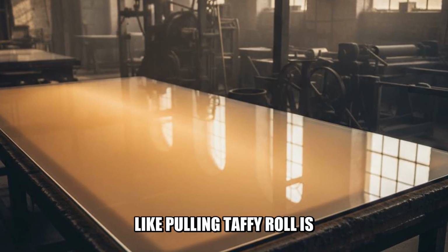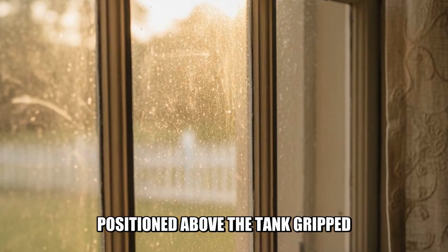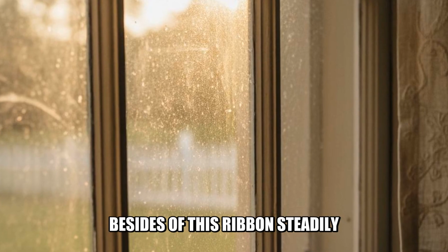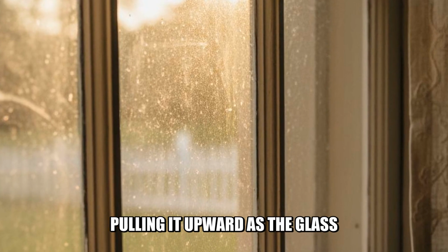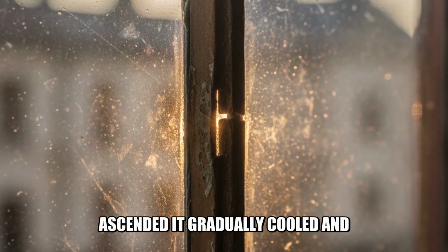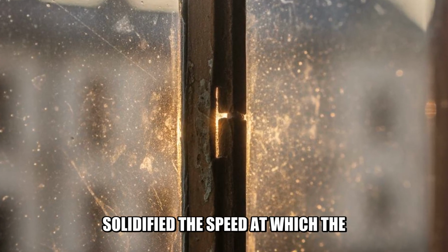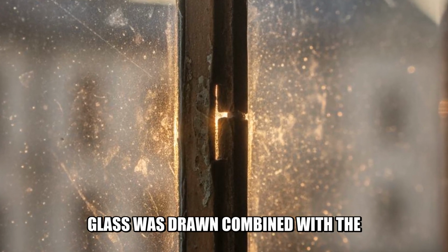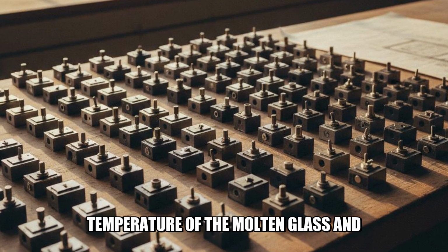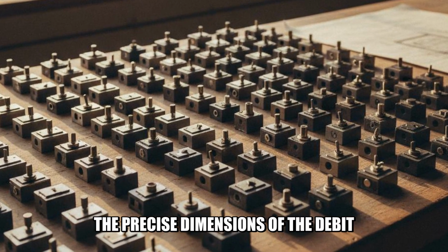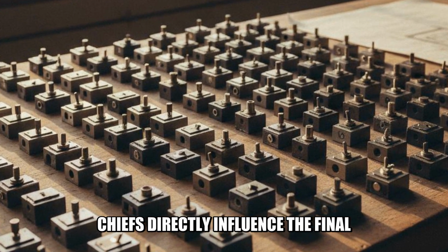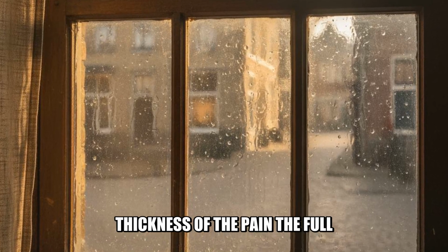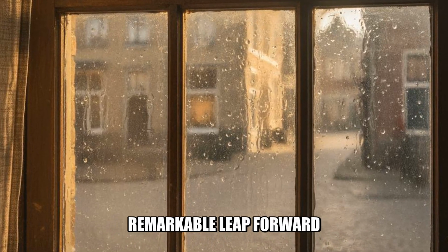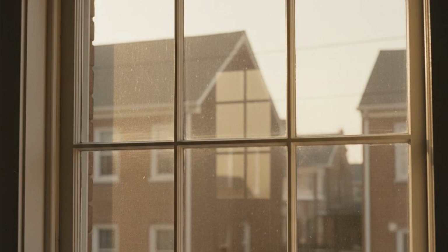Much like pulling taffy, rollers positioned above the tank gripped the sides of this ribbon, steadily pulling it upward. As the glass ascended, it gradually cooled and solidified. The speed at which the glass was drawn, combined with the temperature of the molten glass and the precise dimensions of the débiteuse, directly influenced the final thickness of the pane. The Fourcault process represented a remarkable leap forward.